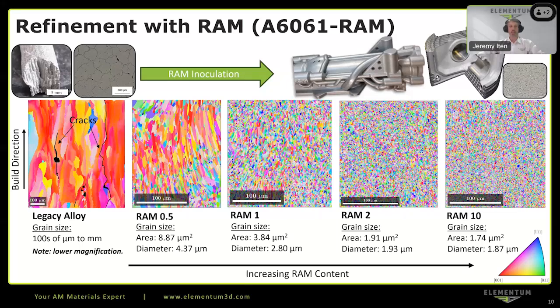And you can see on the left, that's the legacy 6061 aluminum composition alloy. When printed, you get this columnar grain structure with a high degree of texturing and orientation of those crystals. And you get cracking in between those crystals, making it functionally unusable. Once you add in RAM to a RAM1 or RAM2 type level, that 2 in this case represents a nominal volume percentage of the product phases formed in the reactive process, you get a very fine equiaxed microstructure.